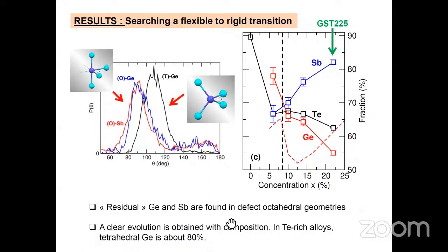We find a clear evolution with composition of those typical geometries. We find for the twofold tellurium a continuous decrease from 90% down to 60% for the 2 to 5. We find a decrease of the tetrahedral fraction for germanium from about 80 to 55. That's the fraction we found for GST 2 to 5 previously. And this can be eventually compared with the binary GeTe, where we could find a minimum in this tetrahedral fraction for germanium.